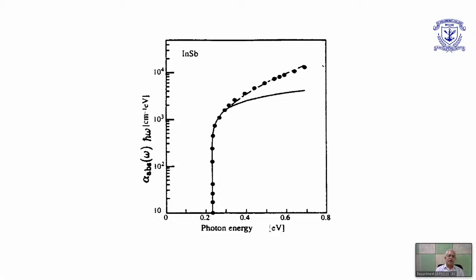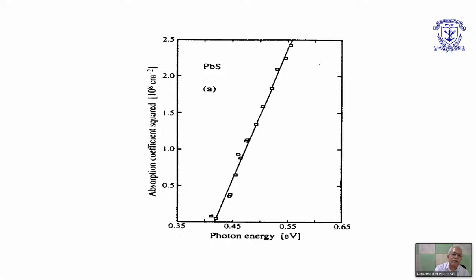So absorption coefficient versus photon energy, which means the experiment is done over a range of wavelengths of light, is seen to be as shown here. And the point where it touches the x-axis gives us the estimate of the band gap. So this is a very simple concept. We can also plot the square of the absorption coefficient as a function of photon energy, which gives us a straight line. And for a lead sulfide sample, this straight line intercepts the photon energy at around between 0.4 and 0.45 electron volt. And that is the band gap of the sample.